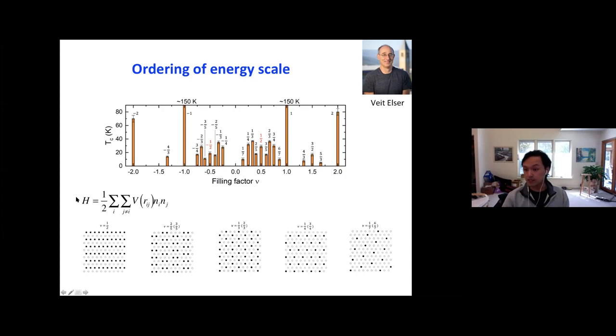And in particular, in this classical model, you would expect a perfect electron-hole symmetry around filling factor 1/2, because you can think of the filled side as particles and the empty side as holes, right? So 2/5 and 3/5 is just inverting the filled side and the empty side. So the TC is almost exactly symmetric around filling factor 1/2. And that's really just captured by the simple theoretical calculation as well.